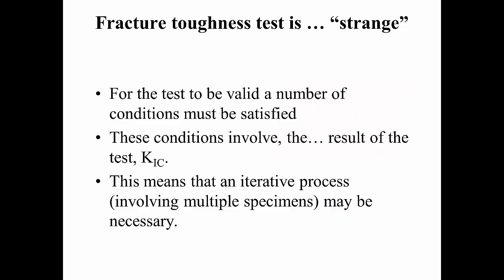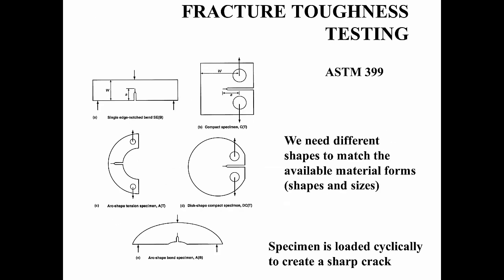So the next thing that we will discuss is how do we measure fracture toughness. And I want to say that this is a different test than others that you have seen. It is strange in the sense that for the test to be valid, some conditions need to be satisfied, and these conditions are not known quantitatively a priori of the test. So the conditions involve the result of the test, and essentially that implies an iterative process involving multiple specimens in order to get the right value for the plane strain fracture toughness. So there is an ASTM standard, as with most of the tests, and the number is shown here in the notes.